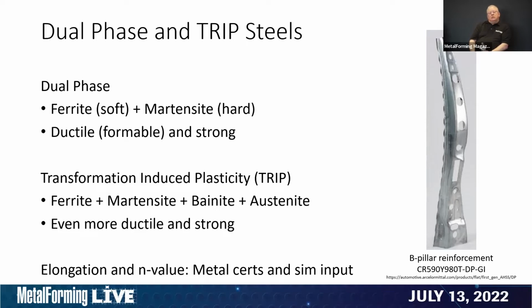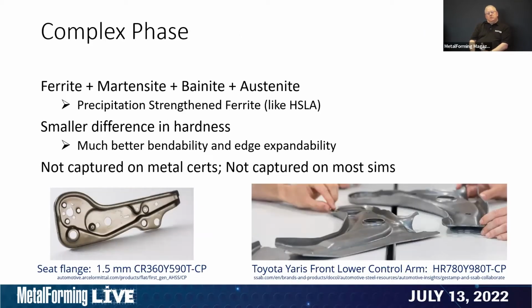There's another common, increasingly used type of advanced high strength steel known as complex phase steels. We've got some examples that are shown on the screen now, and you see they're really not deep drawn parts, but what makes these parts unique, where the features and characteristics of complex phase steels are best used, is that we have a cut edge that is expanded. So complex phase steels have really good sheared edge expandability for their strength levels. Substantially better, actually, than dual phase and TRIP steels.